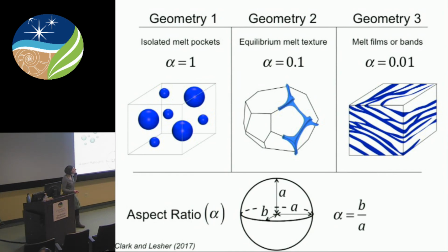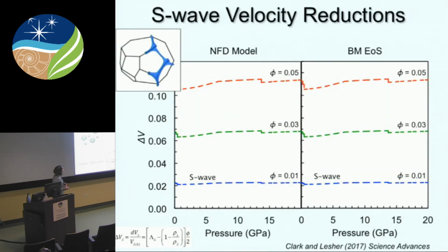And so what she did is she created this thing, this aspect ratio alpha, that can describe the shape of the melt phase along a continuum. So we have things like isolated melt pockets to melt aligned in sheared bands or sheets. And then in the middle here, we have something that's more like equilibrium melt texture, where the melt is aligned along grain boundaries and interconnected.